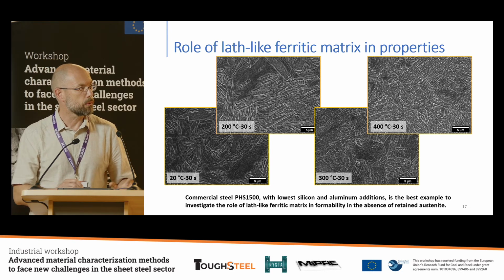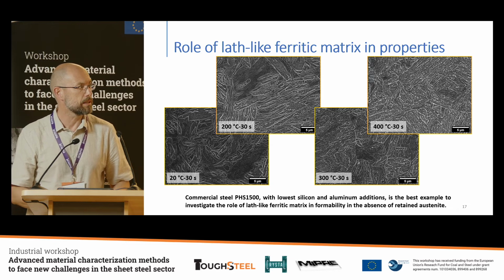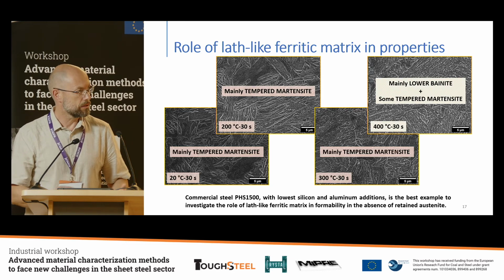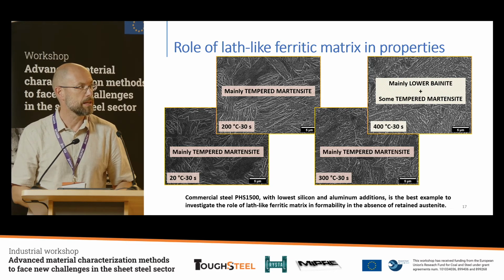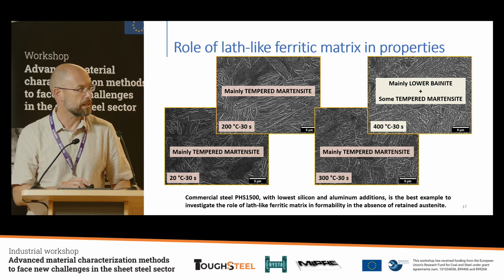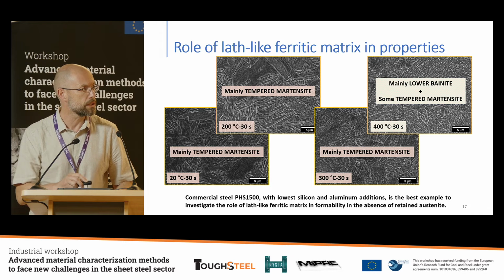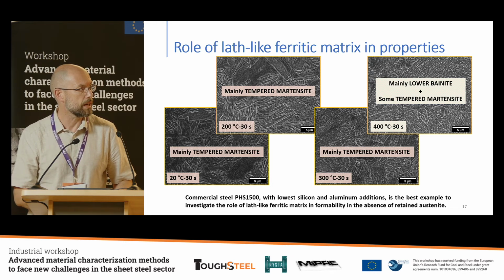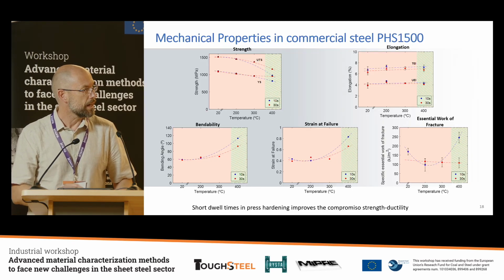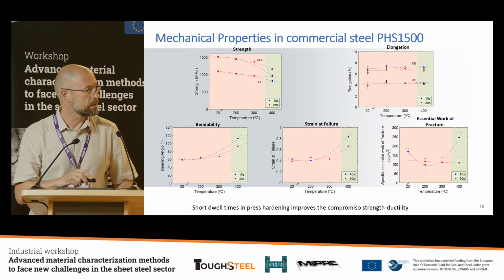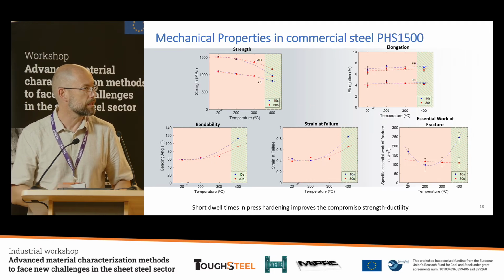In a quick view, they could look similar, but they are not similar when you go deeper inside and you observe the mechanical behavior. And I would like to focus here on this condition, which is the 400 degrees C, 30 seconds closure time, where we have a combination of lower bainite and tempered martensite. This is the green area that I put here in the samples with the different tooling temperatures and the different mechanical behavior.